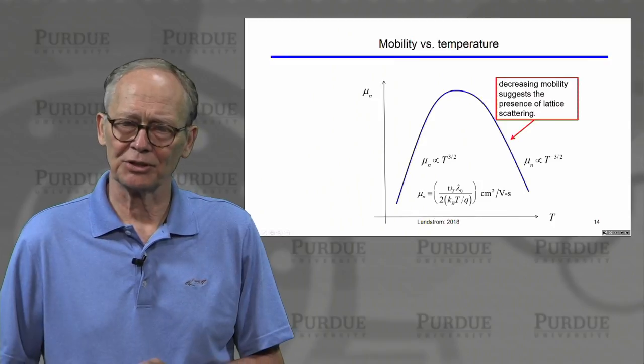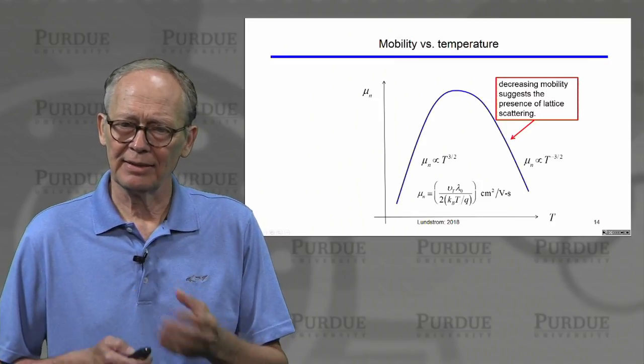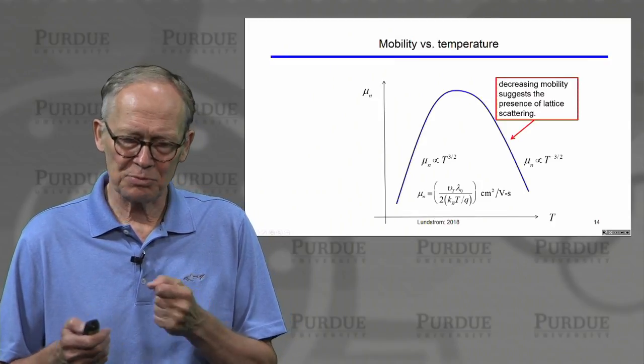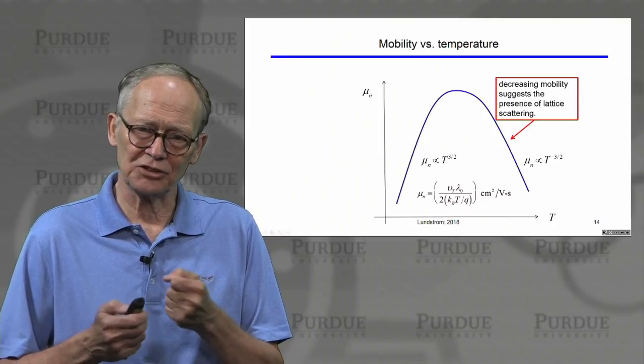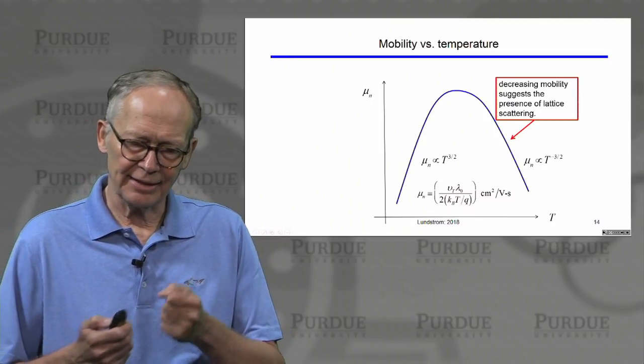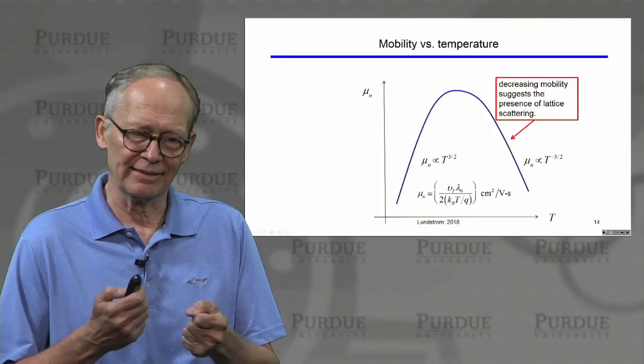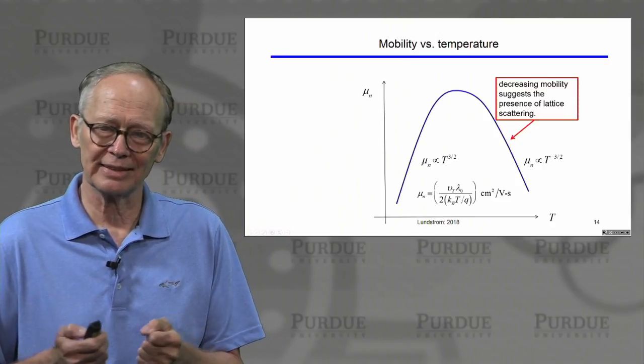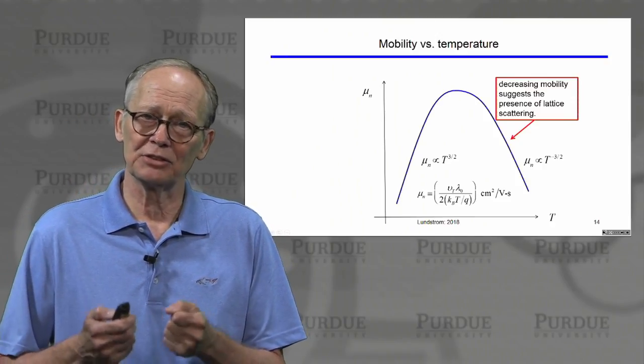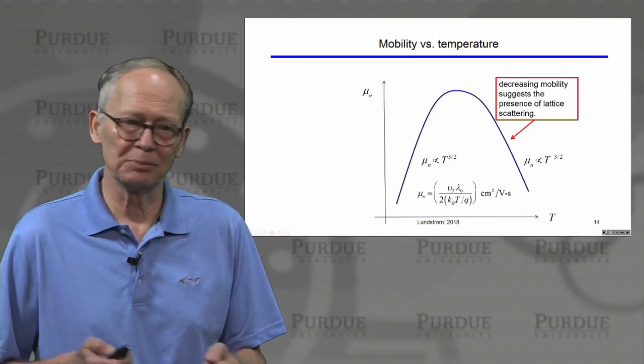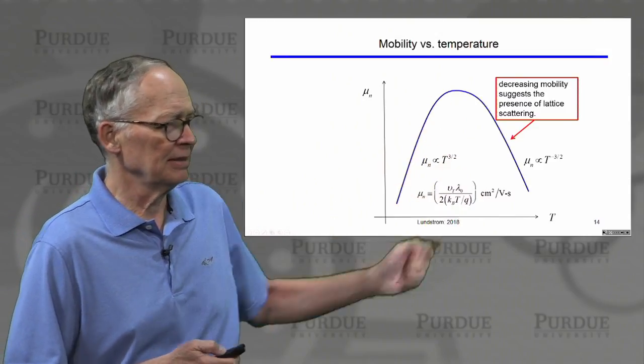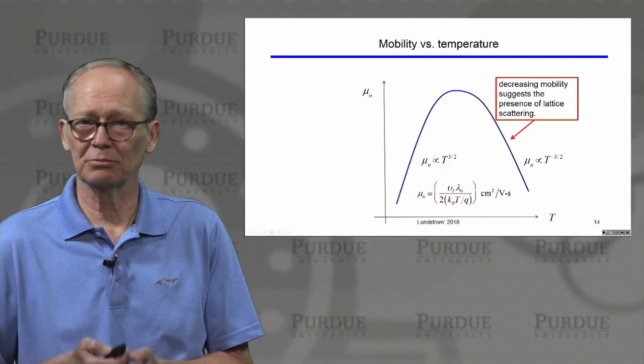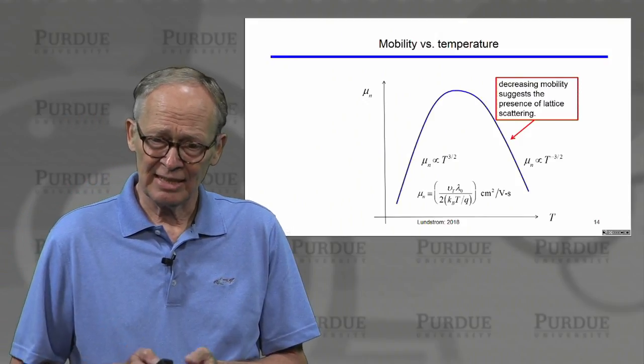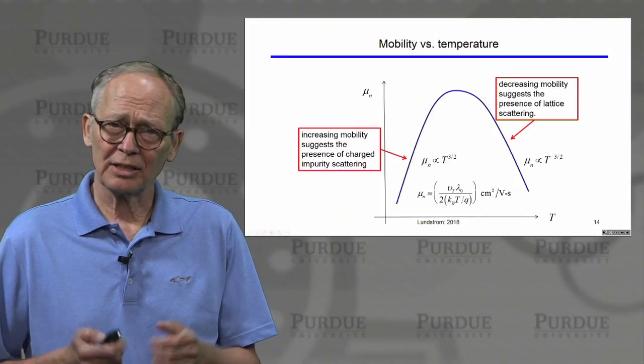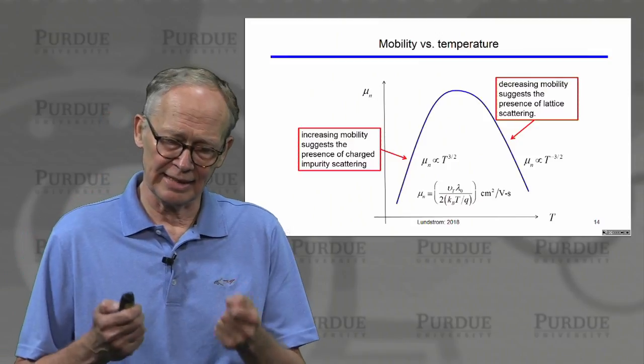At high temperatures, there's much more random thermal motion of the lattice jiggling around. The lattice interacts with electrons and knocks electrons around more rigorously. The time between scattering events drops, the mean free path drops, and the mobility drops the higher the temperature is due to that process. Now, under low temperatures, there isn't much jiggling around of the lattice.